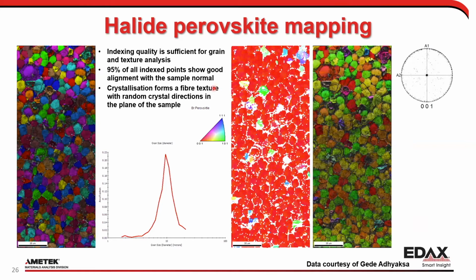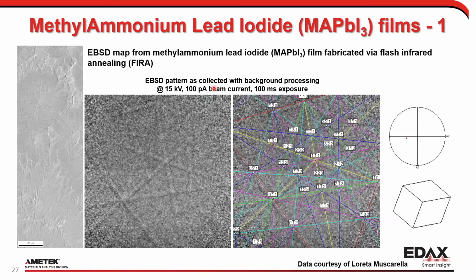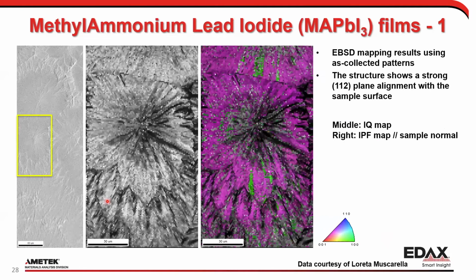So this is a halide perovskite material. There are also these thin films, the methylammonium lead iodide films that people are working on. This is doing what's called flash infrared annealing. Again, I don't claim to be an expert on that. But here you can see at 100 picoamps, they're able to get high quality results on this. And of course, they're able to map as well. This is a map of this sample over here. We can see both the structure of the material as well as a very strongly textured part of this, in this case in the 112 alignment. Again, just another example of this.